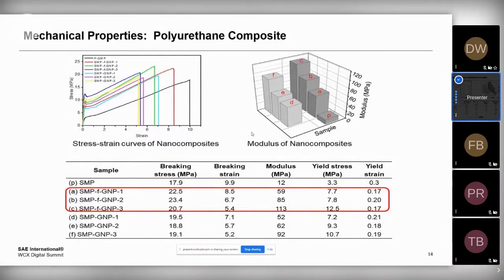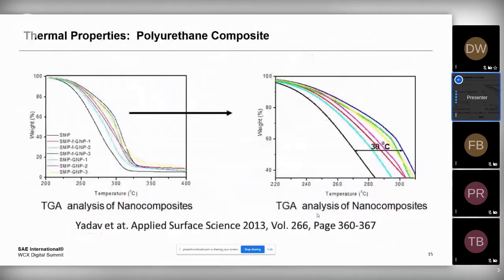The whole issue of load transfer has a very significant impact upon the types of properties you're going to achieve. They found that with respect to your breaking stress, it can increase by as much as 10 or 15%. Your breaking strain improves similarly, but then the impact upon modulus, in terms of what you were able to accomplish with load transfer, improved vastly, by like 1,000% in some cases. So there's a vast difference, a massive amount of difference, between what you can do with a graphene that's been properly functionalized for your application and properly dispersed for your application versus one that is not.